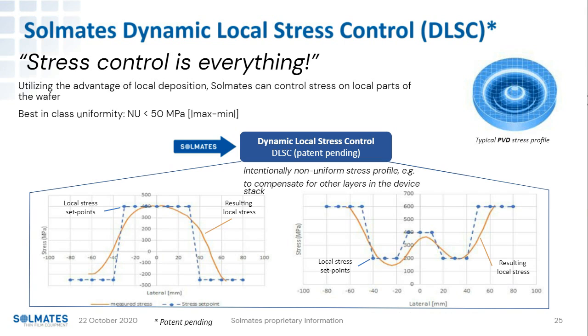So either we go for best-in-class uniformity, and that means that we can go to 50 megapascals. We think we can do even better. At the moment, we're hitting the limits of the metrology tool. So the metrology is limiting progress here. But we think we can do way better than 50 megapascals.